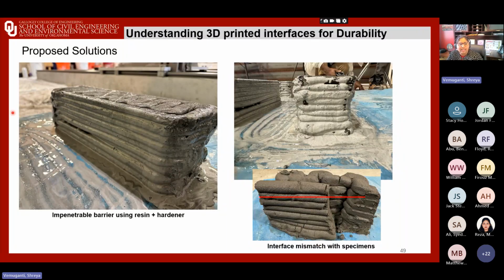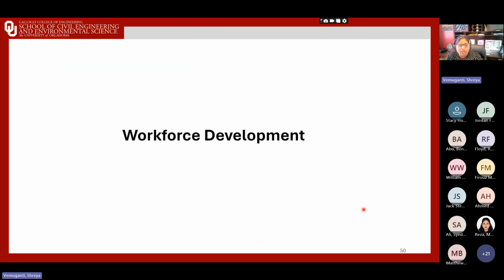So here you see this resin saturated 3D printed concrete specimen. Here also we see some sort of a mismatch. Essentially, we're trying to understand if tailoring interface geometry itself, just trying to mismatch these layers of interfaces, can we reduce the exposure risk to the reinforcements within?